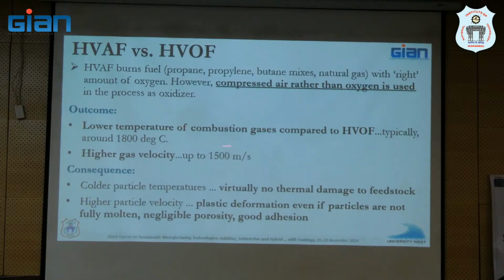Why is this interesting? Why are both of these interesting? Lowering the flame temperature means that there is no thermal damage to the feedstock. We spoke about what different defects can be present in a thermally sprayed coating. One of them was oxidation. You could say that in some cases there is also elemental depletion. None of that happens if the flame is a little bit colder, right? And second, of course, is higher velocity, where you get extremely good adhesion.